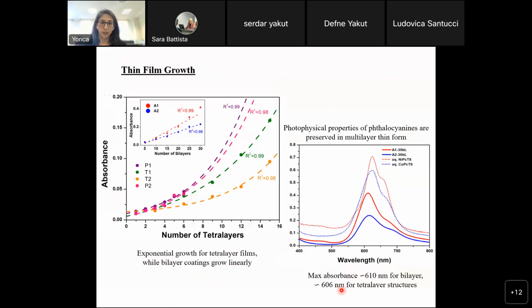So first, I need to check the thin film growth in both cases. I mean, both the bilayer structure and the tetralayer structure, in the presence of nickel and in the presence of copper. And as you can see here, in the presence of tetralayer structures, we have an exponential growth, but in the presence of bilayer structures, we have a linear growth. This might be due to the higher concentration of polyelectrolytes in the overall thin film system. So they might be swelling, diffusing into each other, but here we have only single layers of polyelectrolytes after each other.